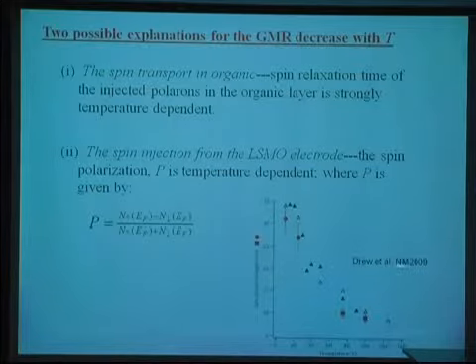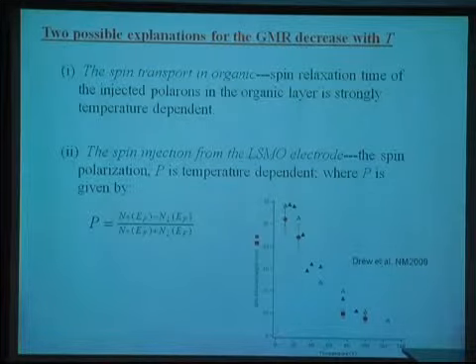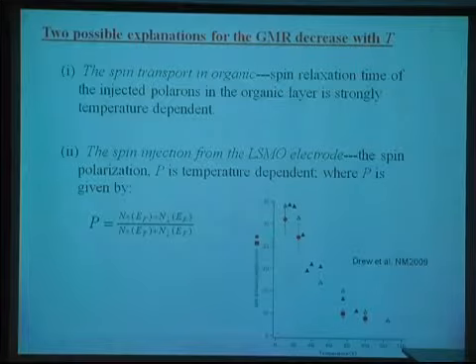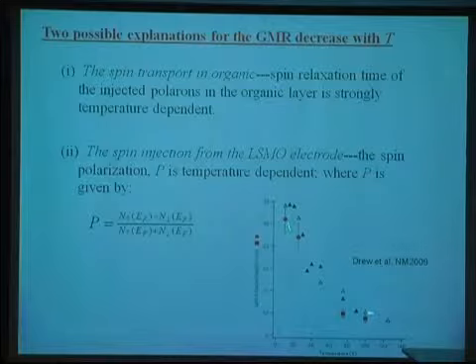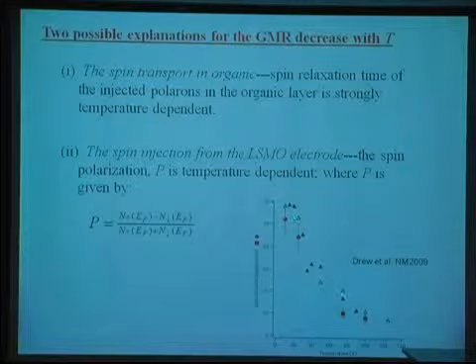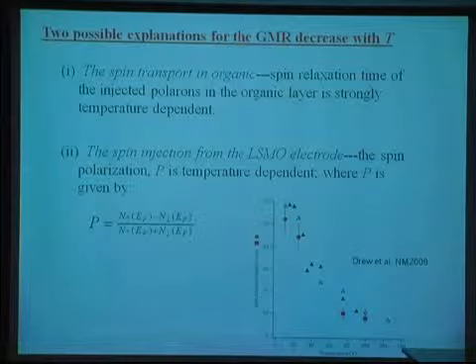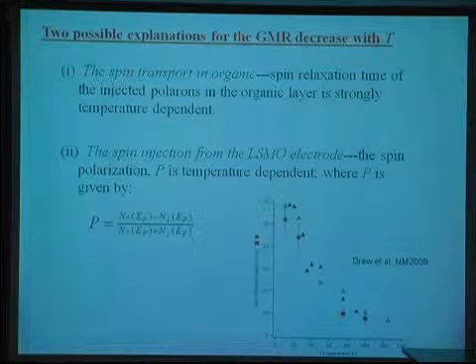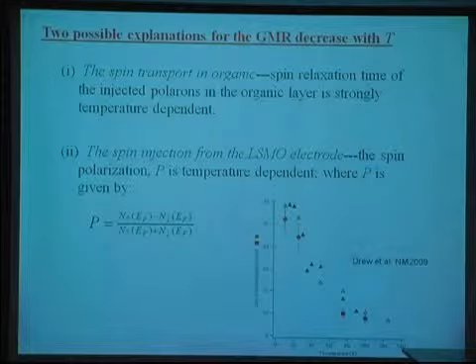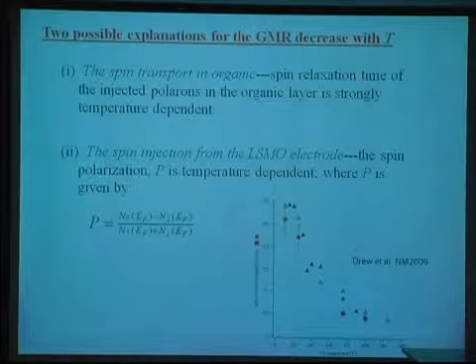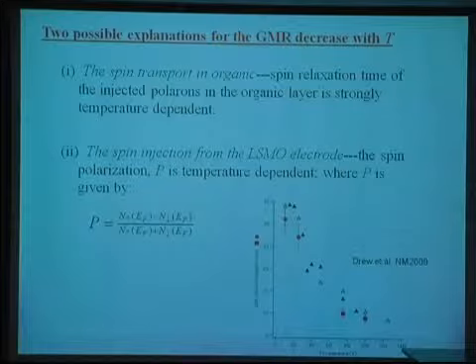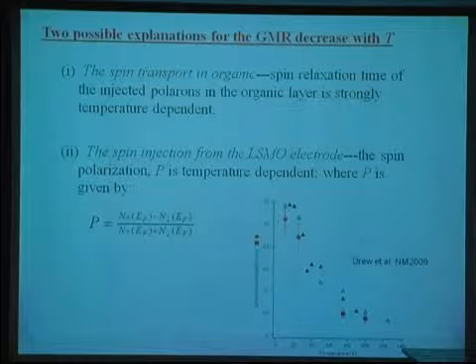Actually, in 2009, Drew et al. reported that they can detect the spin diffusion length versus temperature, and you can see the spin diffusion length in the Alq3 material goes down very fast with respect to temperature. What is the mechanism for the spin relaxation? I think it is mainly because of electron spin-phonon coupling. So this is the definition of the spin-lattice relaxation. But isn't a phonon spinless? How can a phonon affect a spin? This is a good question.